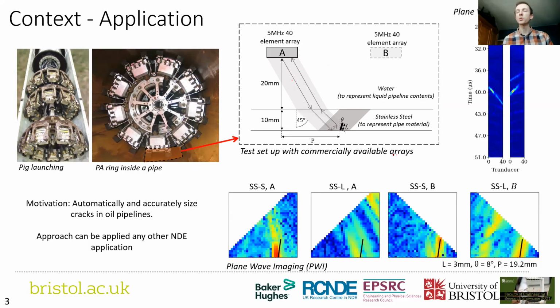So you've got to decide on what array path you're going to use, and we found that half skip imaging is the best. So that's the one drawn here, where you've got the sound coming through and it's shear in the plate, bounces off the back wall, hits the defect, comes back to your array. Because we're transmitting in shear, which is where the oscillation is perpendicular to the direction of travel, we can go shear, shear, shear, or we can have a mode conversion off the defect to longitudinal. So that means it's with direction of travel, and we get 4 images.